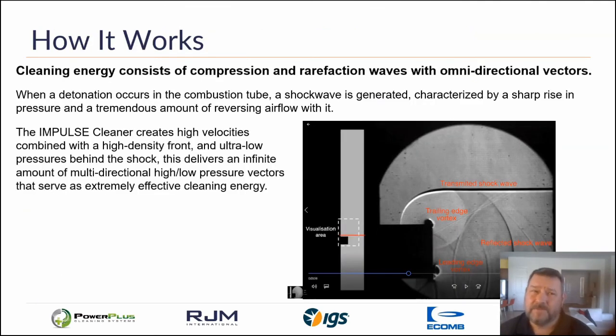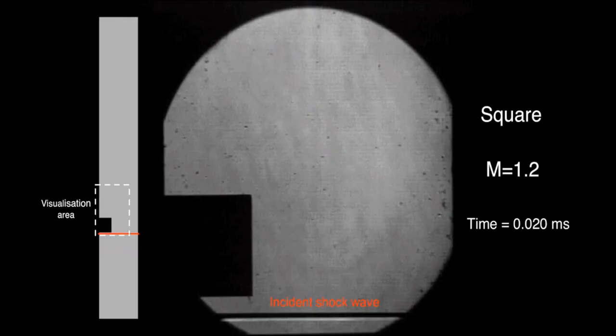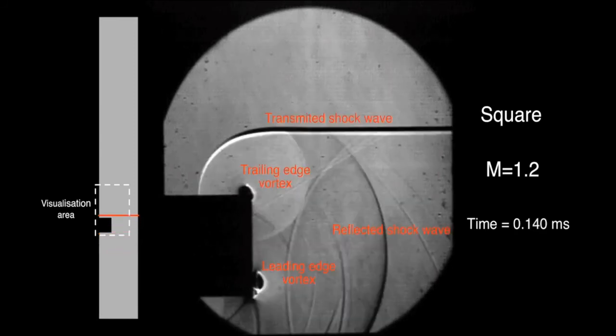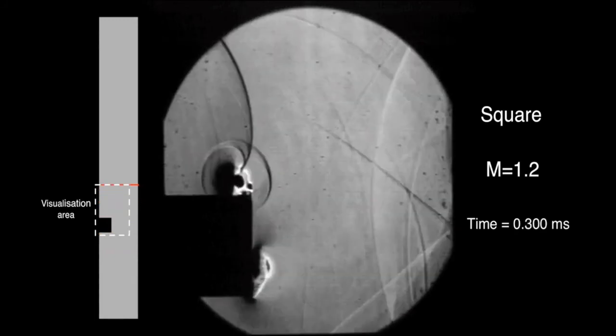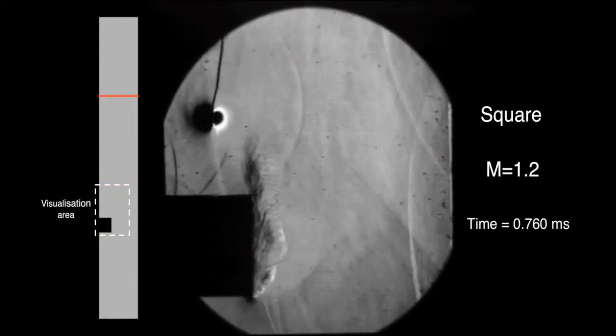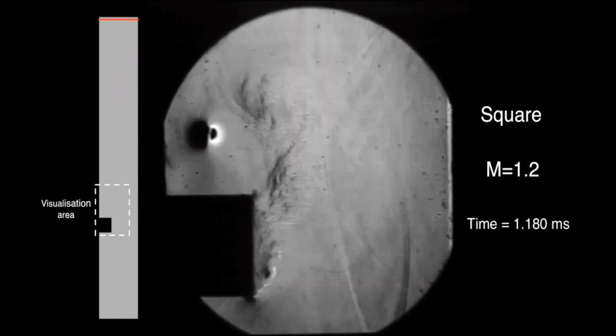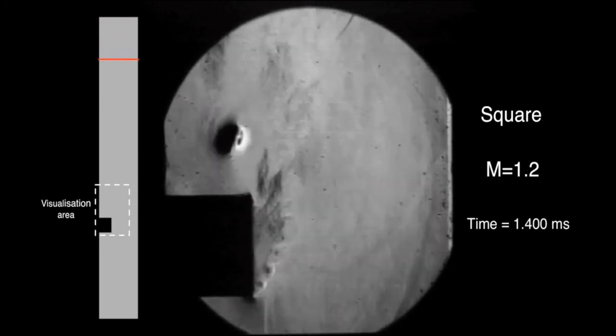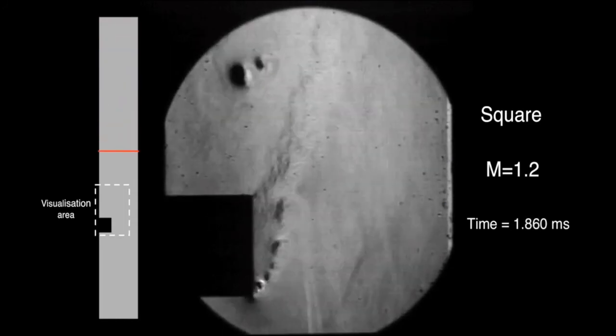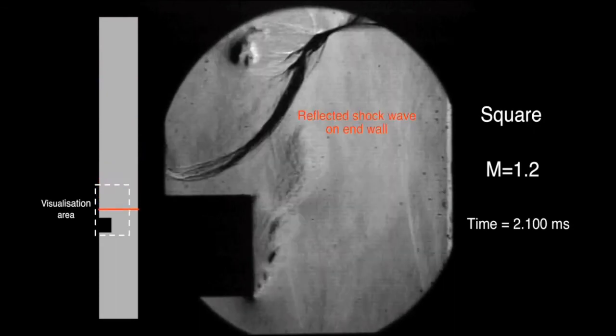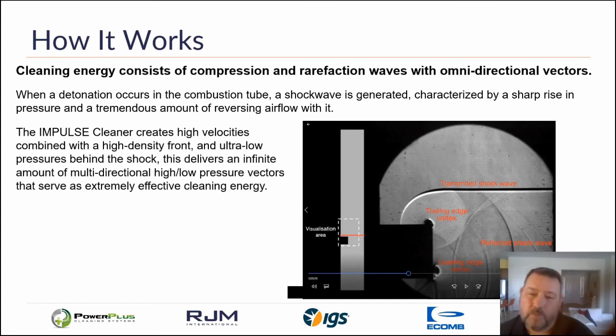Cleaning with a shock wave consists of compression and rarefaction waves that are omnidirectional in their scope. So when a single shock wave is produced, you have a highly compressed front followed by a rarefaction or low pressure, and then a trailing eddy current or vortex that creates a sweeping action following that high pressure front and the low pressure swing. That change or displacement and the eddy current behind it create a large amount of opposing vectors or pressure swings that will serve to very effectively dislodge deposits. That was one shock wave. We do this between 20 or 30 times in a single cleaning cycle, providing an excessive amount of cleaning energy.